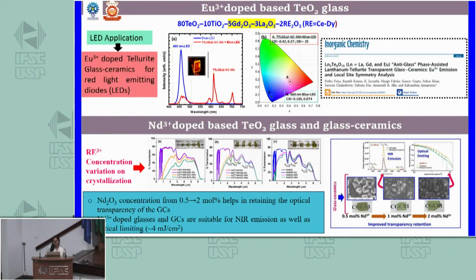Now, we have also doped europium, which is a commonly known spectroscopic probe, and with the help of europium, we have studied the anti-glass phase precipitated in our glass ceramics, which turned out to be C2v. Not only that, we have also studied the effect of rare earth ionic radii in controlling the transparency of the glass ceramics and found that increasing the rare earth concentration helped in retaining the transparency.